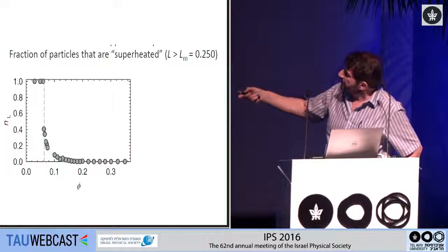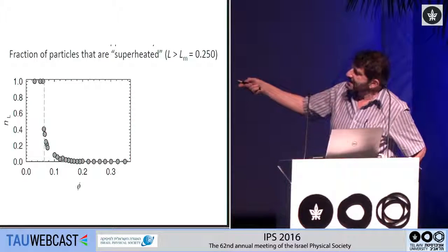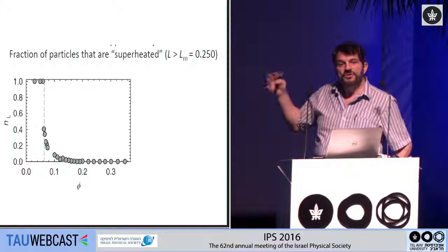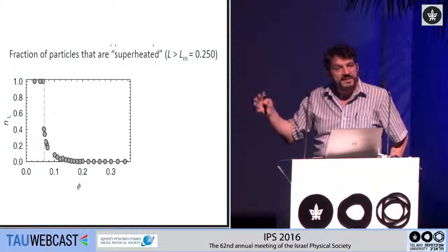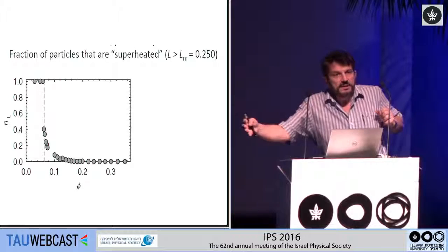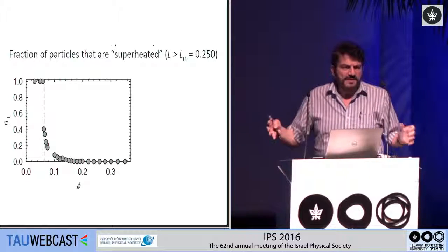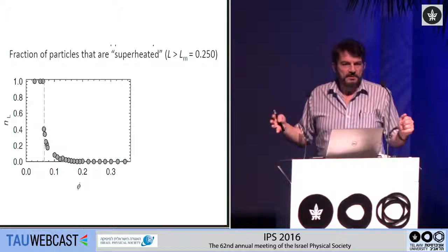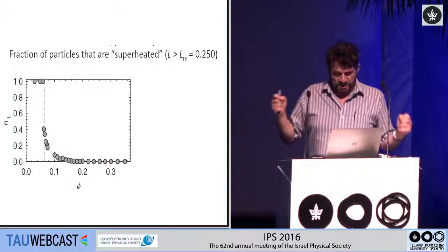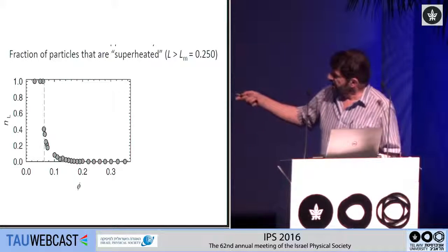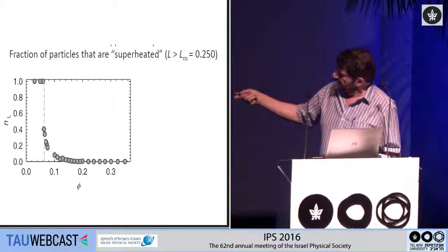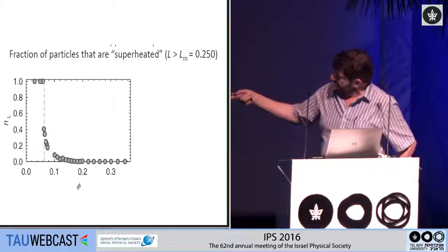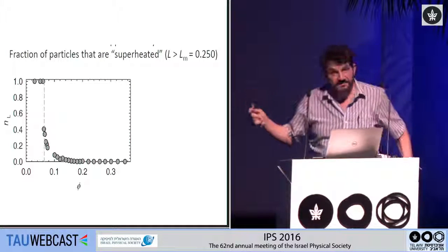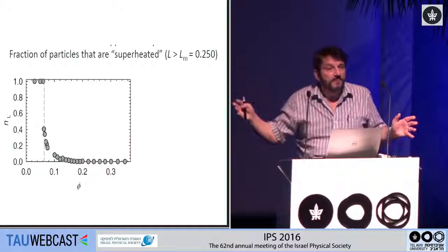And you can plot the number of particles that exceed the average value that would cause them to melt. And these are essentially particles that are fluctuating this huge amount, and therefore you could call them superheated particles. They're much hotter, they have much larger fluctuations than otherwise. And you see that the number of particles, or the fraction of particles, as it approaches melting, gets very, very large, and ultimately, of course, the system melts.